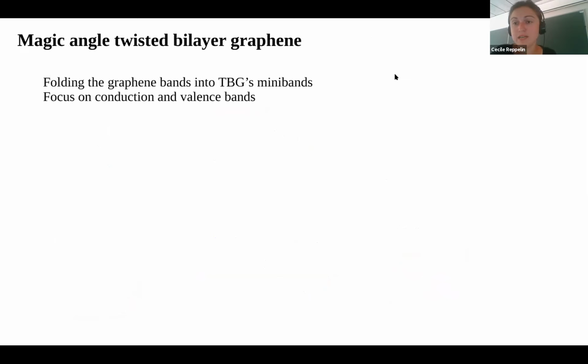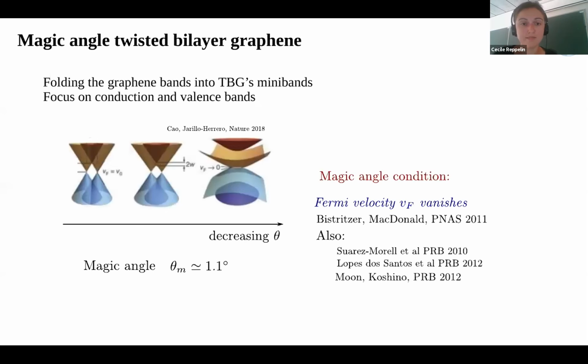Now, as you have your superlattice potential, you are folding the original bands of graphene several times. That will create thousands of mini bands. And of those bands, we want to focus on the conduction and valence bands. Thanks to the tunneling between the top and bottom layers, gaps are opened, and the conduction and valence bands are separated by a gap from lower and higher bands.